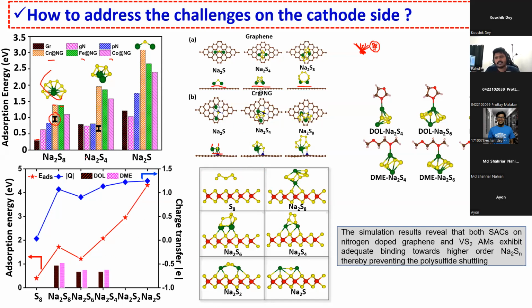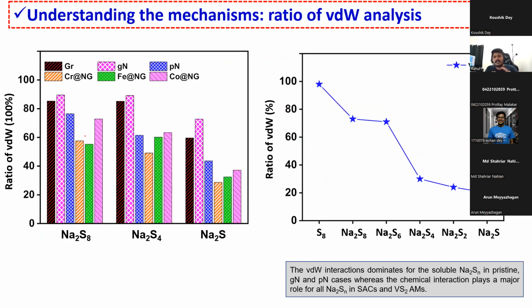And I was always talking about the interaction energy between the electrolyte and the polysulfide, right? What is it? These are the electrolyte solvents, DOL, dioxolane, and dimethoxyethane. These are the electrolyte solvents commonly used in sodium sulfur batteries, and this is the interaction energy between these two. If the interaction energy of this system is higher than this system, then it can trap the polysulfides without sending them to the electrolyte. Now we have found that the adsorption energy of the single atom catalyst as well as VS2 is very high compared to that of the electrolyte. So we have to find the reason why it's high. Then we do the analysis.